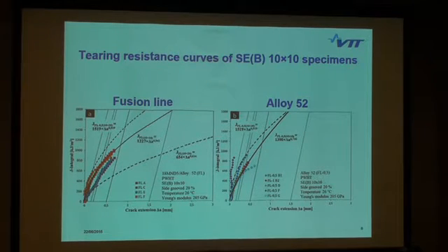Okay, so explanation here. It was clearly seen on the fracture surface that these specimens had initiated on the weld metal side, on the tough alloy 52 weld metal side, and the 10 times 20 specimens that I showed, which were the reference situation, initiated on the heat affected zone side. So there's a clear evidence of crack location affecting the tearing resistance.